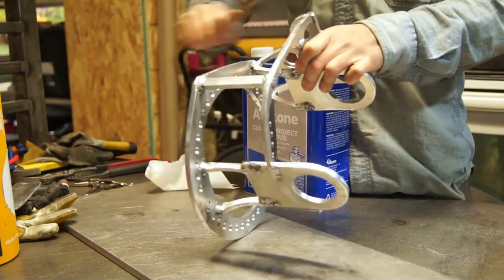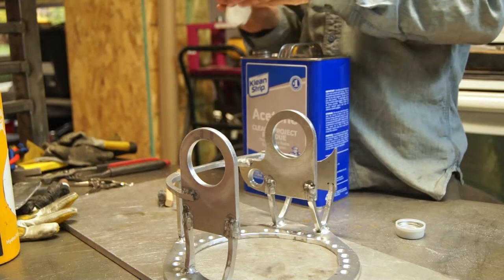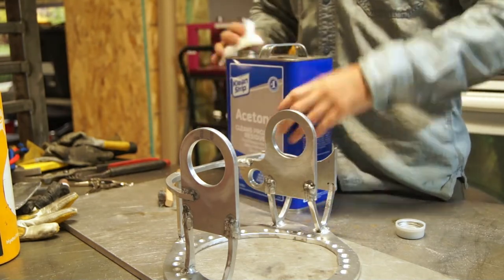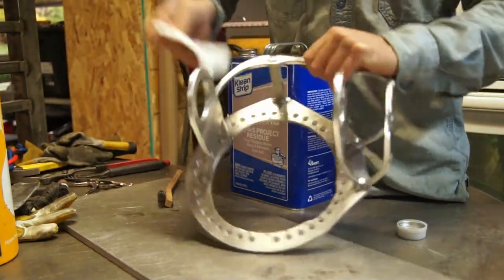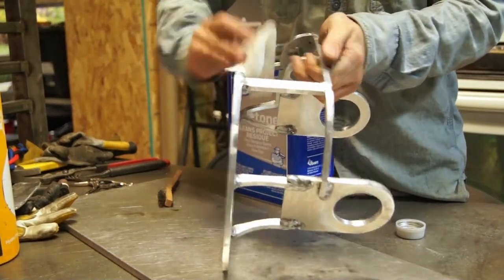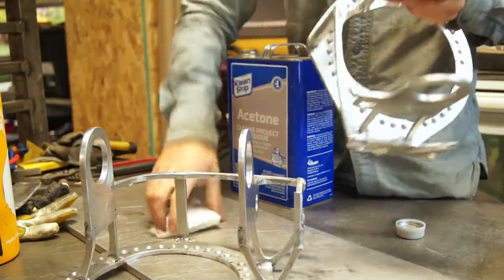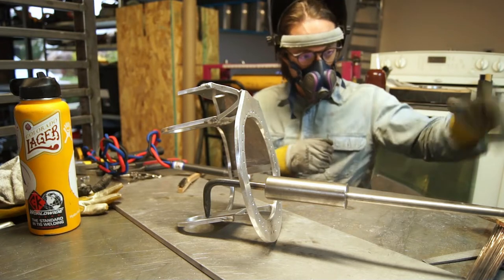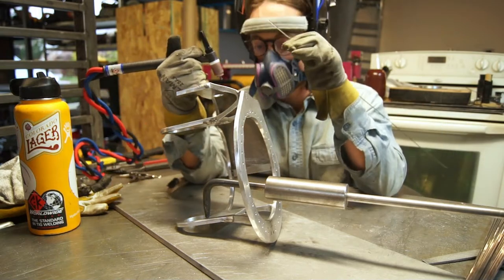Doing a little brushing, which I don't do a whole lot of. I don't have too much trouble getting the oxide layer off aluminum. I'm also cleaning it, which I'm doing less of now. If you watch any YouTube video or talk to welders, anyone who welds aluminum says cleanliness is next to godliness because you get black stuff they call pepper in your welds. I've just found I did a few without cleaning them and it just wasn't happening, so I essentially took it out of my workflow because it's time consuming and I have a lot to do.